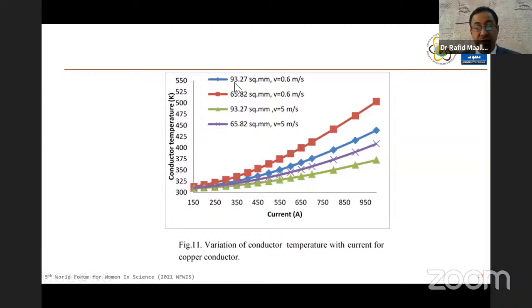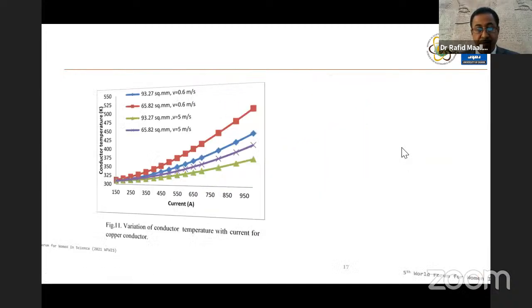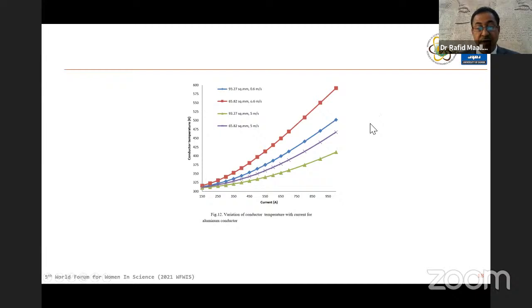But when the cross section increased, there is lower temperature. That gives us the equation: the heat dissipated from the conductor is proportional to the length of line, and inversely proportional to the area of the cross section. Also, this is the variation of conductor temperature with the current for aluminum conductor, the same trend as for copper. Also, the small cross section and the small velocity give higher temperature than the higher cross section.